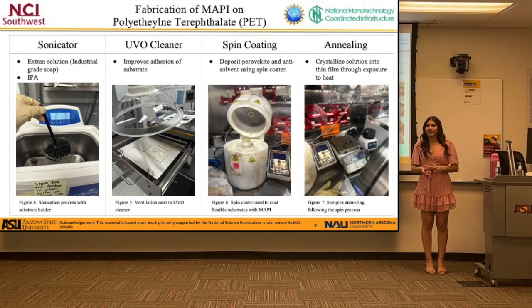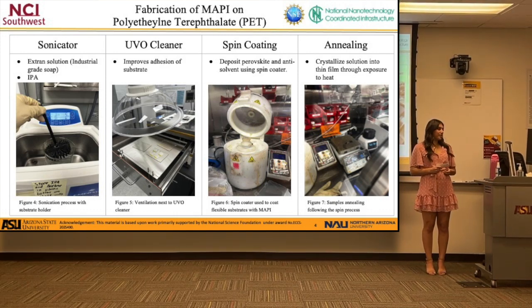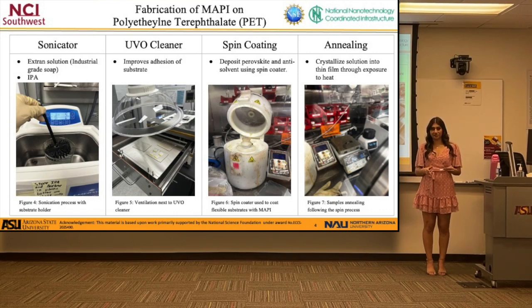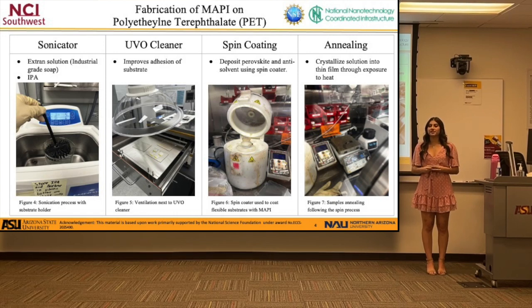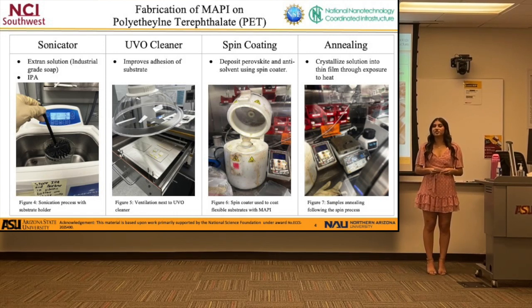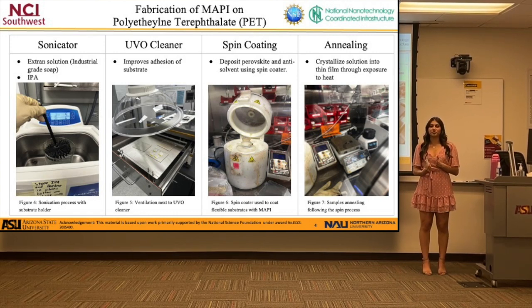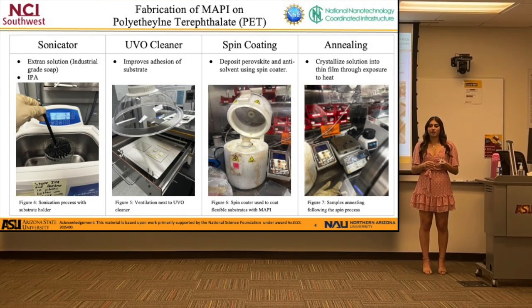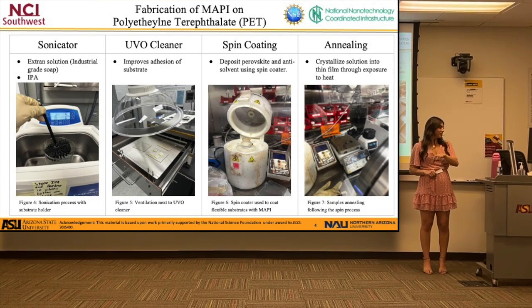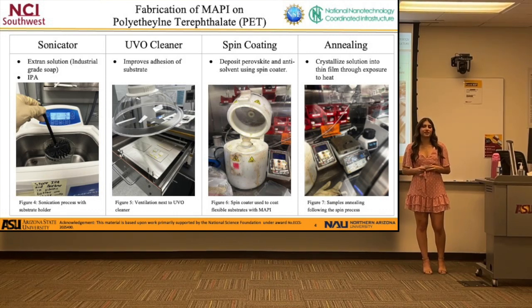As far as fabricating the device itself, which is MAPI, the perovskite, on the polyethylene terephthalate, which is also known as PET. First step in this process is using the sonicator, which essentially just gets rid of the debris on the substrate itself, and it uses sonic waves to shake off the debris almost. And we submerge the substrate in solutions known as extran, which is industrial grade soap, and IPA.